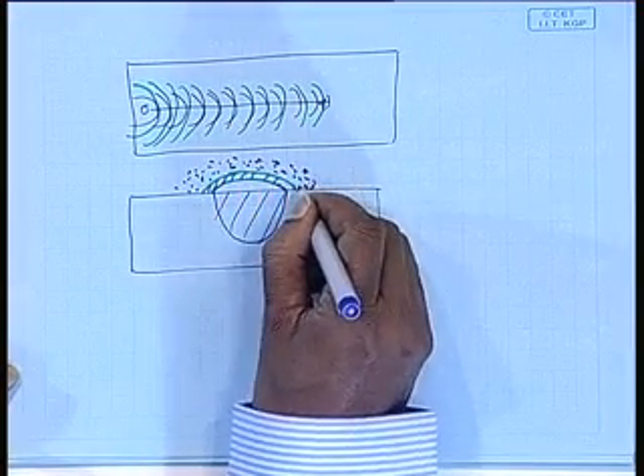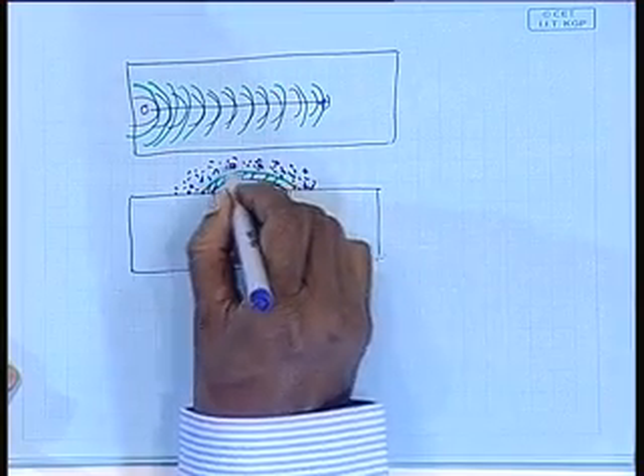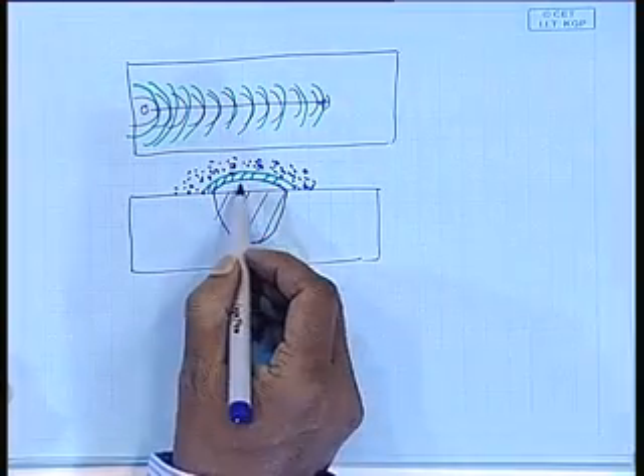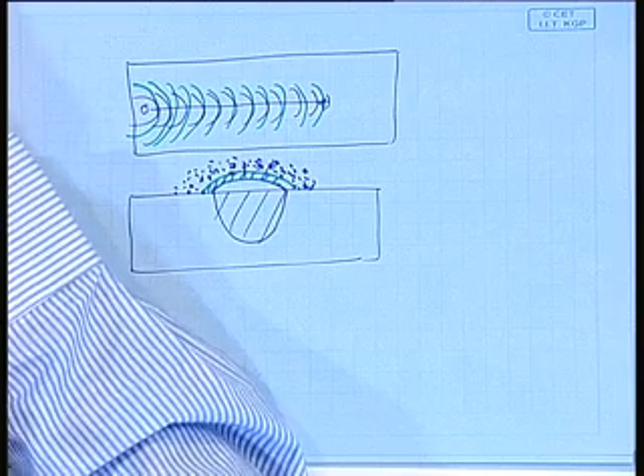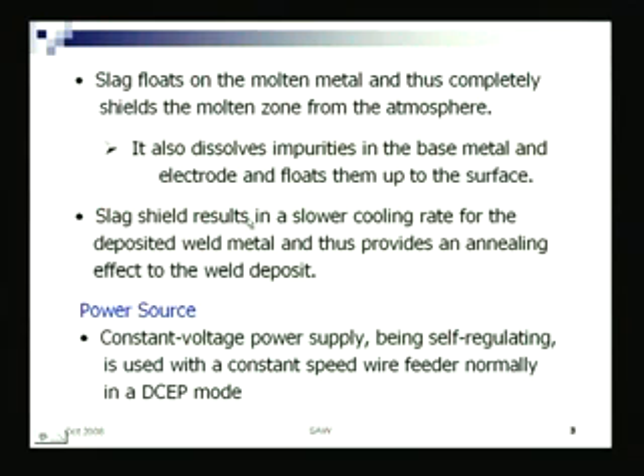So what is happening in the process? You have total shielding of the deposited metal. The molten metal eventually becomes the deposited, solidified metal. So the heat loss from here is minimal, it is having an insulating kind of shielding. This slag shield along with the flux lowers the cooling rate of the deposited metal. Once the cooling rate is reduced, it provides an annealing effect of the weld deposit.